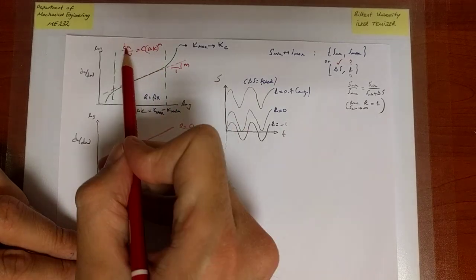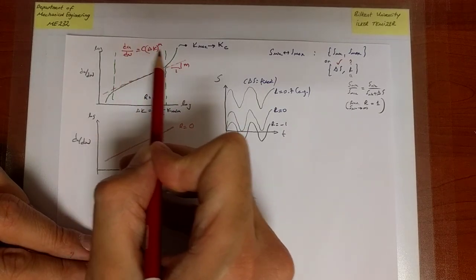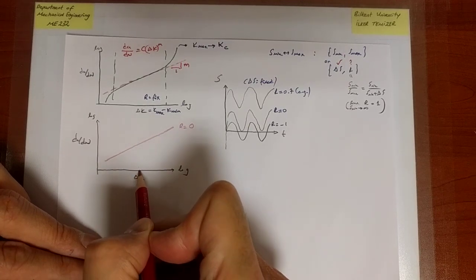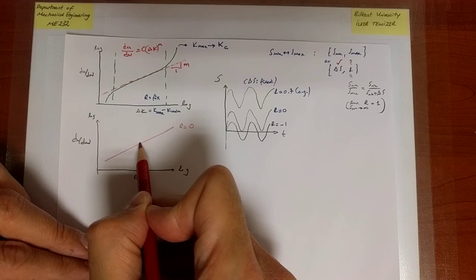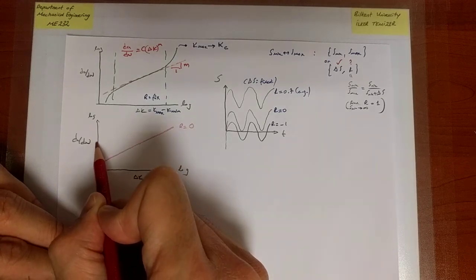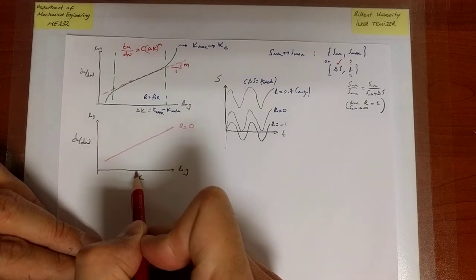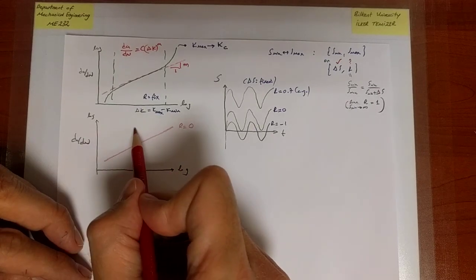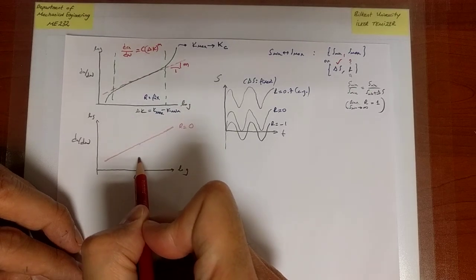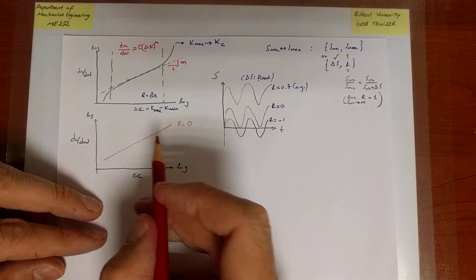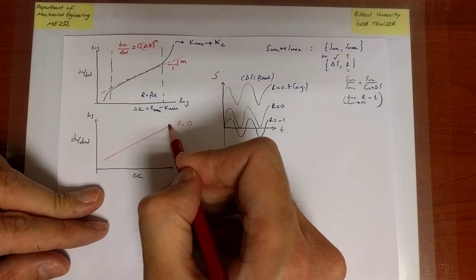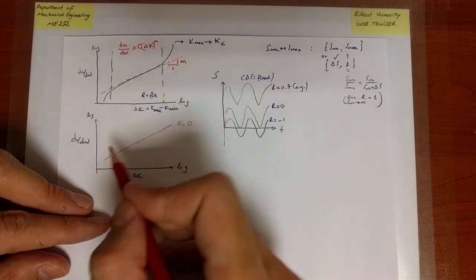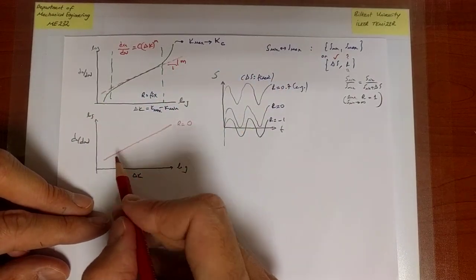Okay, right? It is the line that corresponds to this law. In other words, for any given delta K, the point on the line is predicting the rate at which the crack grows. If for a given delta K the line were higher, then the crack growth rate would be estimated to be higher. If it were lower, it would be estimated to be lower, etc. So now, this is the prediction of our model for R equals 0. That comes from, if you like, experimental data, within or up to the high range.